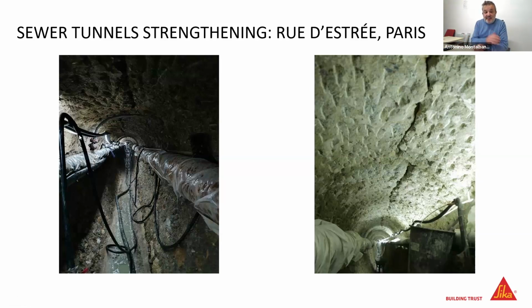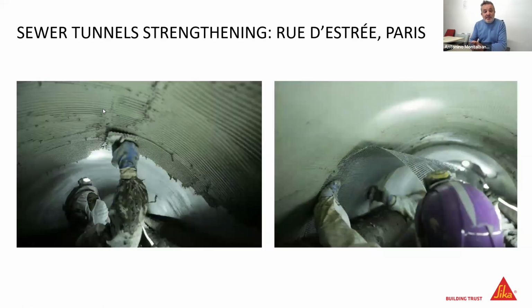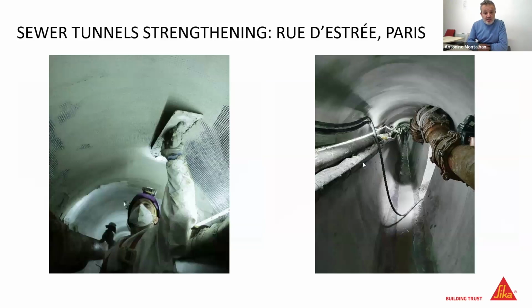In this case, it's a humid substrate, so the application of the FRP was not possible, and even the roughness of the surface was not suitable for the application of the FRP, so we applied the Sika carbon grid system. So you can see the application of the first layer of the mortar, then the embedment of the carbon fiber grid, easy to handle. You can see that it's extremely easy to handle and to embed the grid in the first layer of the mortar, then fresh on fresh